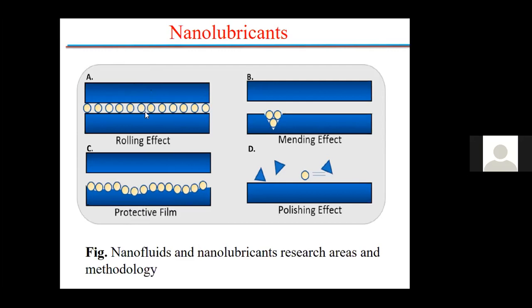It's based on the structure of the nanoparticle. So the nanoparticle becomes a protective film, or has a mending effect. In the mending effect, it happens like this. The nanoparticles go and settle in the valleys or cracks of sliding or rolling contact machine elements.